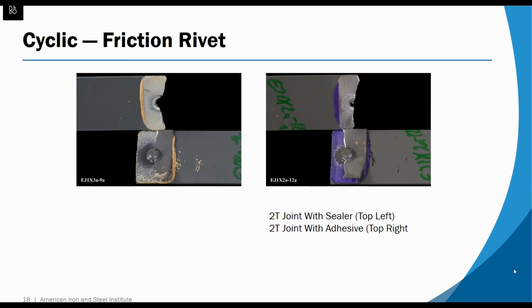In cyclic testing, and this is a typical theme we've seen with mixed material, many of them cause a cyclic failure at the interface to the joining element because there's a stress riser there.